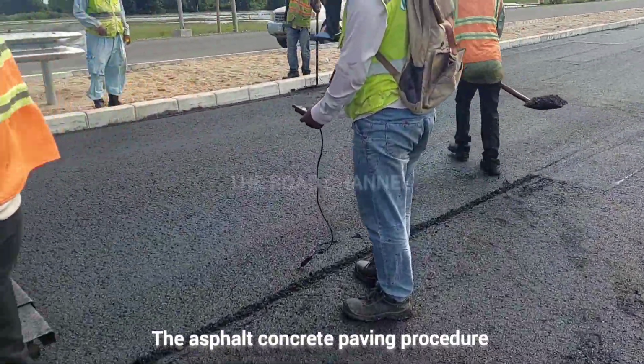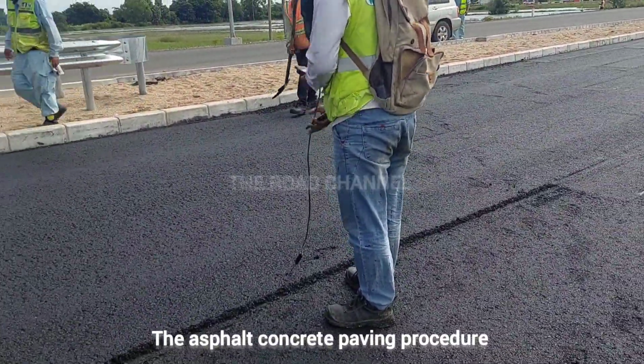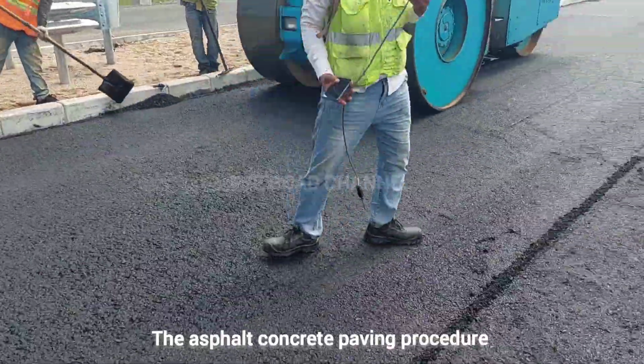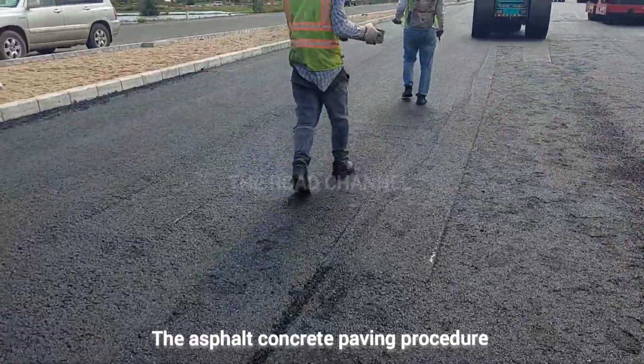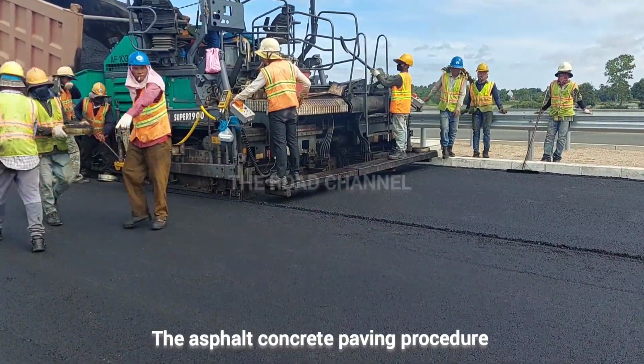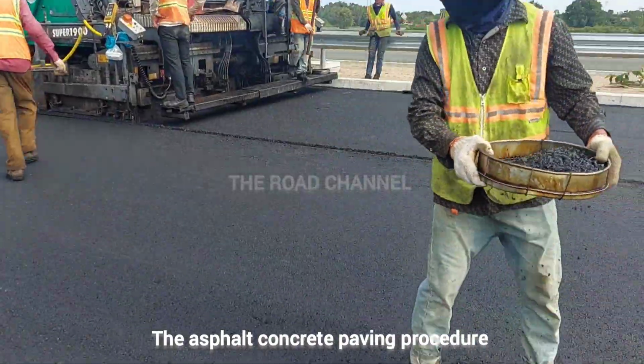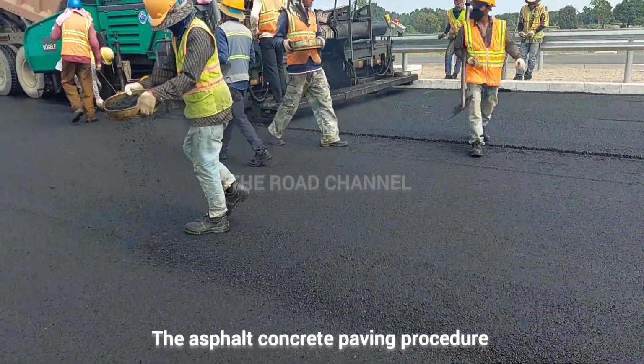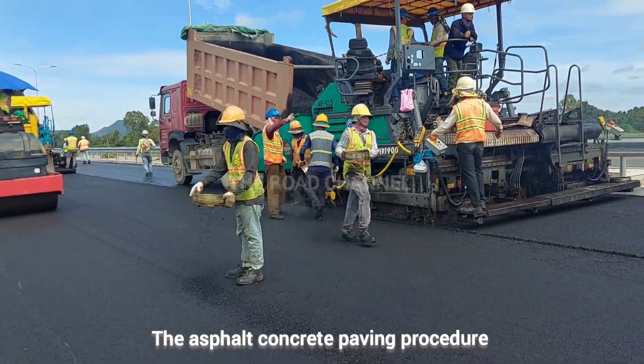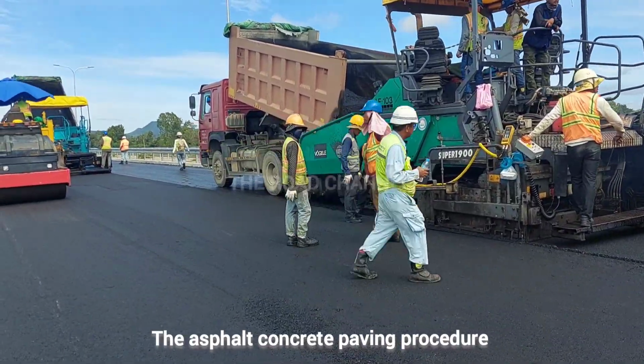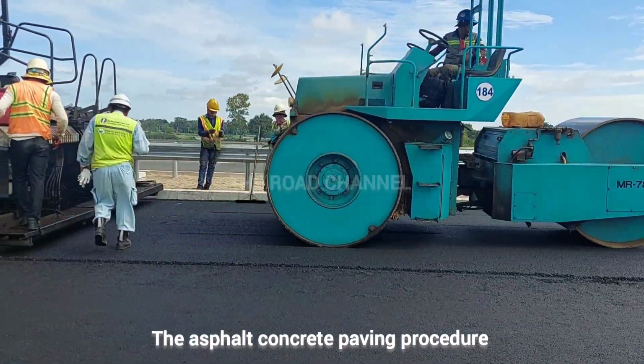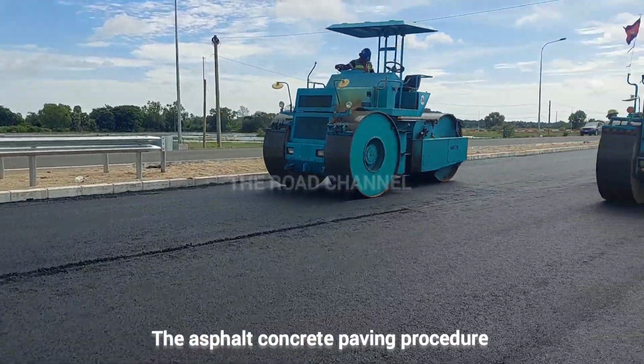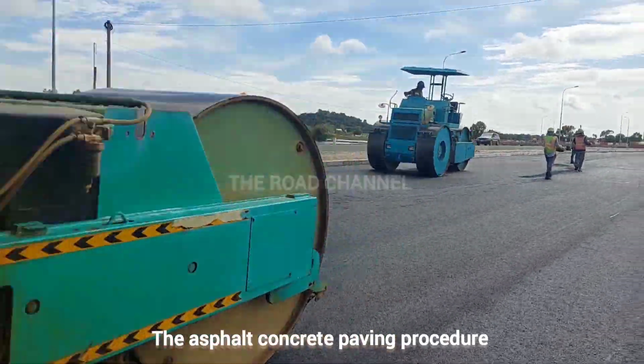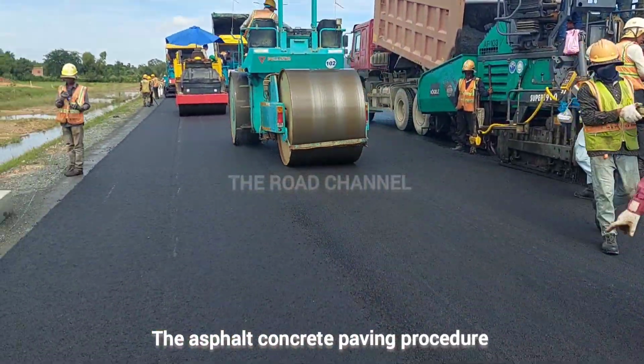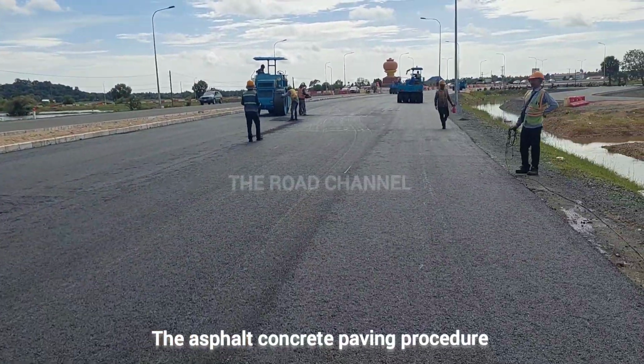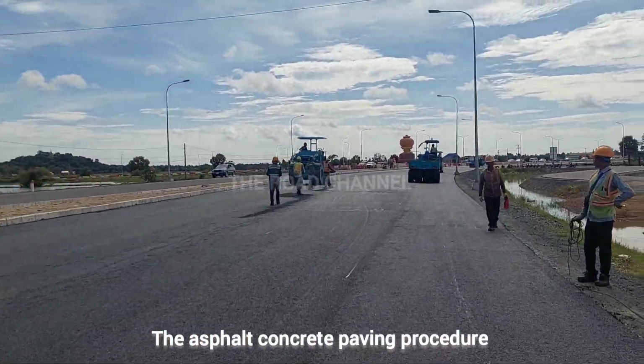1. Pre-paving checks. Base surface preparation. Ensure the base course is clean, dry, and compacted. Verify that the surface is free from loose material, dust, or standing water. Check for proper slopes and cross-falls to ensure drainage. Tack coat application. Verify the correct tack coat type and application rate, typically 0.25 to 0.50 kilograms per square meter. Ensure uniform spraying and proper curing before paving.